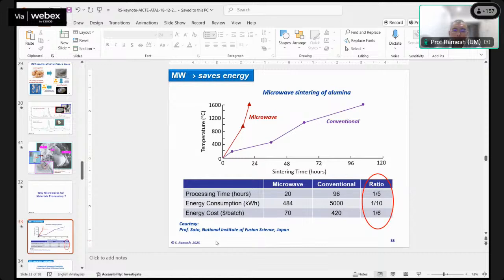Here's some study carried out by Professor Sato from the National Institute of Fusion Science in Japan. He has done the comparison in terms of the processing time to process alumina ceramic versus conventional. For microwave it is just 20 hours as compared to 96 hours for conventional. This is for sintering purposes.